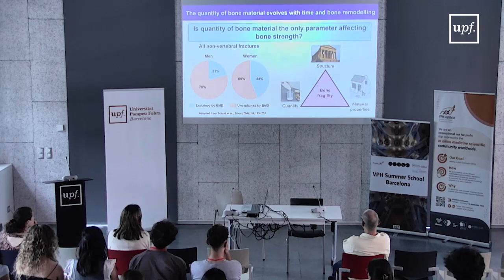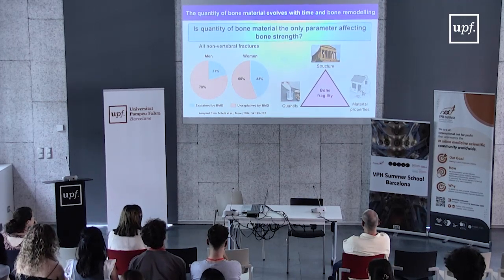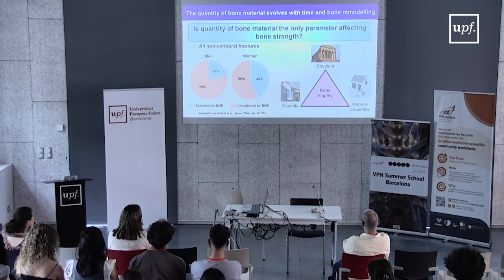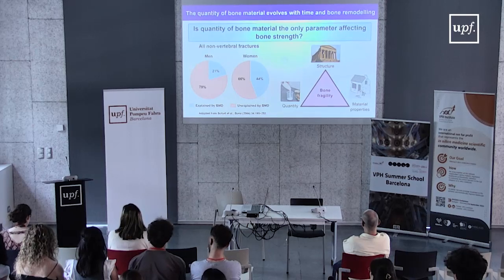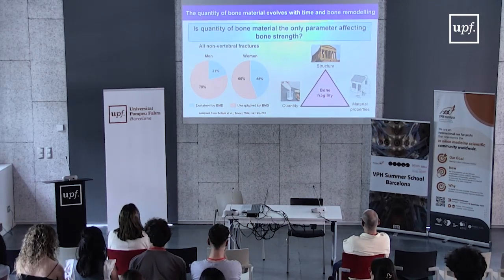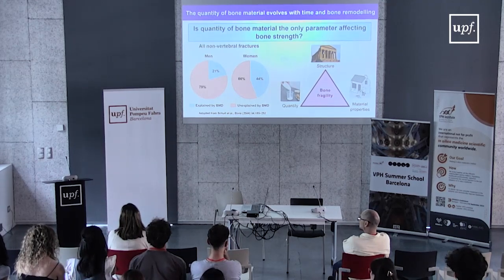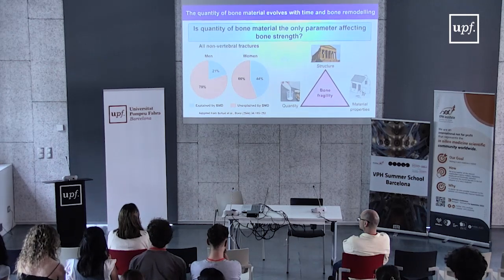It depends, of course, on the quantity of your bone. If you have a really too low bone mass, you're at risk of fracture independently of the other factors. But it depends also on the way that your bone material is organized in 3 dimensions, which is called the microstructure. And it depends also on the material properties, on the quality of your elementary brick inside your bone matrix. If you have alteration of your collagen or alteration of the mineral, you're at risk, independently of the geometry and the quantity, of developing a bone fragility and a bone fracture.